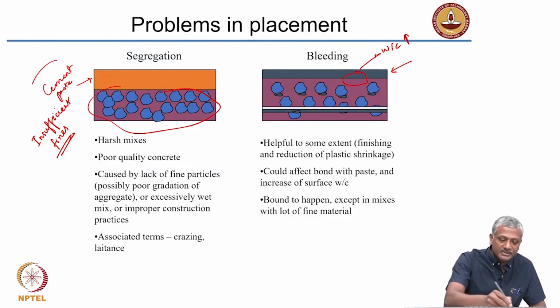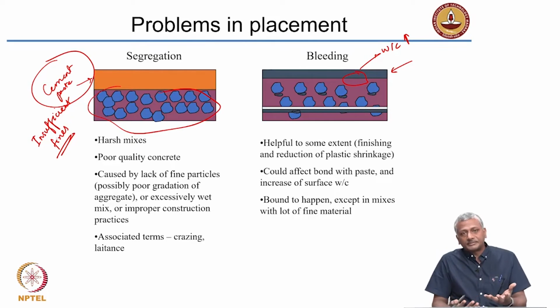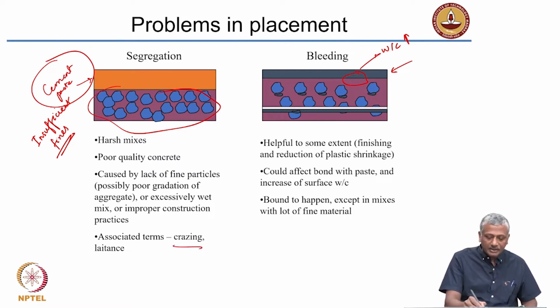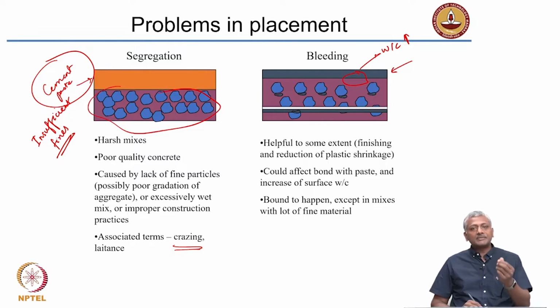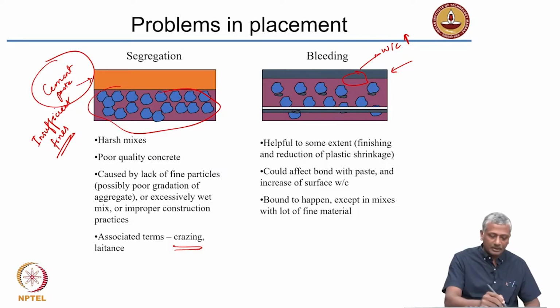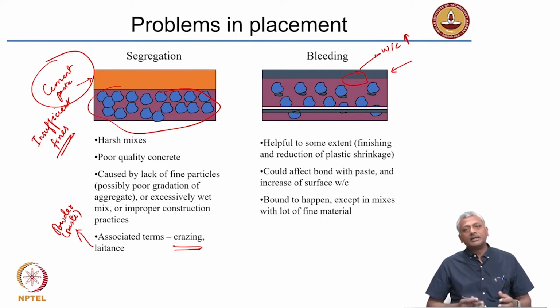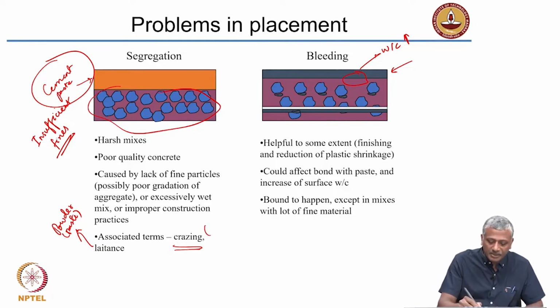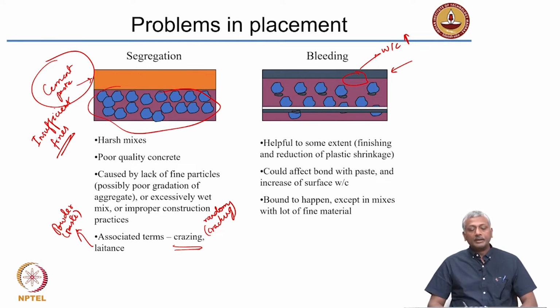Very often when you get the cement paste on the surface, I told you before that cement paste shrinks. If you form this layer of cement paste on the surface, it will shrink and then start getting cracked. That cracking is called crazing. You get these crazing cracks, and sometimes the cement paste will dry off as a powder and comes out, and that's called laitance. The cement paste dries off as a powder and basically gets removed from the top surface. That's called laitance. Crazing and laitance are a major problem. Crazing is basically random cracking of the top surface. So if you lack fines in your mix, either fine aggregate or enough cementitious materials, you are going to be causing these problems of segregation and bleeding.